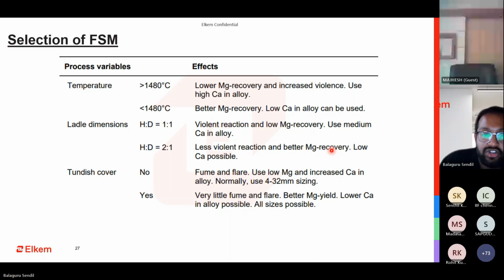If you have a tundish, you have very little fumes and flare. You have better magnesium yield. You can have the lowest calcium possible, and you can go for the correct size of FSM. If you don't have a tundish cover, then you need to go for a coarser, bigger size of FSM. You need to go for something like 10 to 25, 10 to 32, 4 to 32, sizes like that for a 500 kg treatment itself.